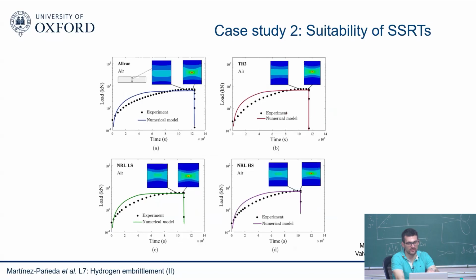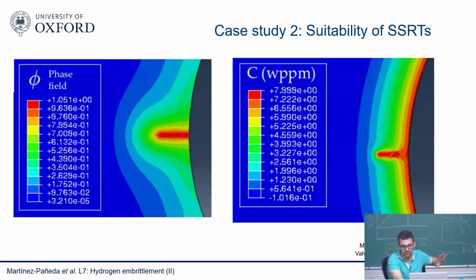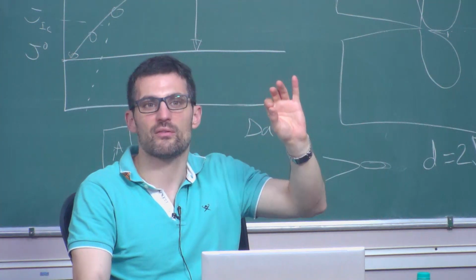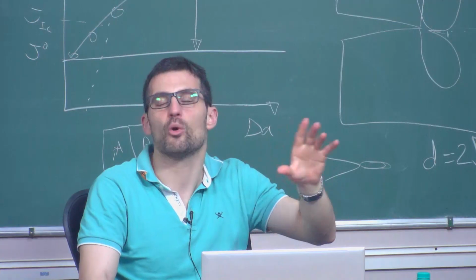Okay. So here, to understand the boundary condition, we use the penalty boundary condition, but it has no influence on the result. So you just need to pick, when you deal with penalty boundary conditions, you have a penalty factor. You are forcing the solution to become equal to the environment in a certain region. So basically what we want is, in this region here, I don't want my hydrogen concentration to be the solution of a transport problem. I want to enforce it to be the hydrogen concentration at the boundary. So I want this to be red. The way you can do that is by adding a penalty factor into your equations. The larger your penalty factor is, the more precisely you will capture this, but you will also bring more convergence issues. So there's a balance basically. You pick your value large enough that it will give you what you expect to see, like you see here, but that it won't cause you convergence issues.